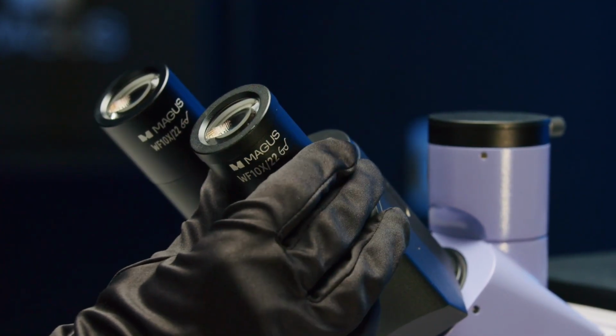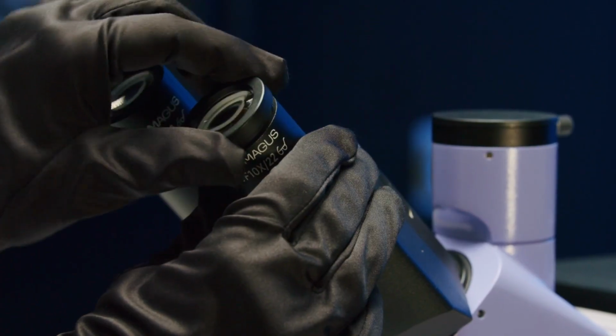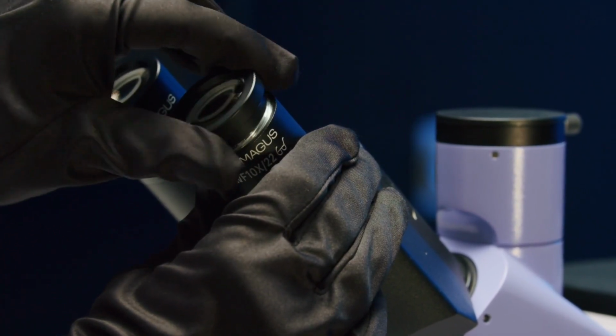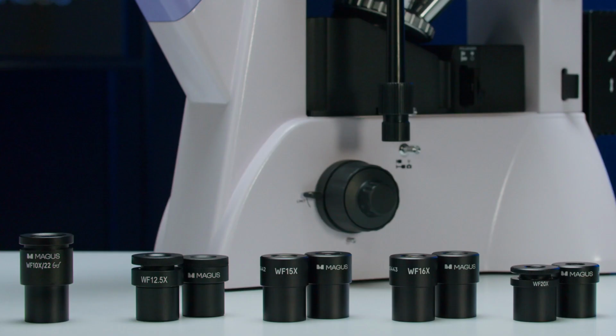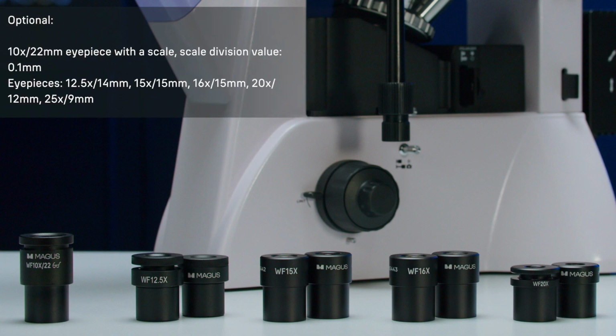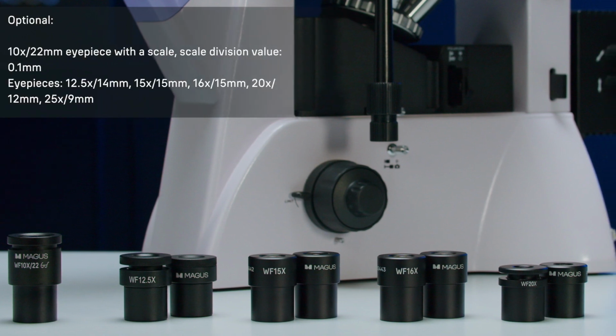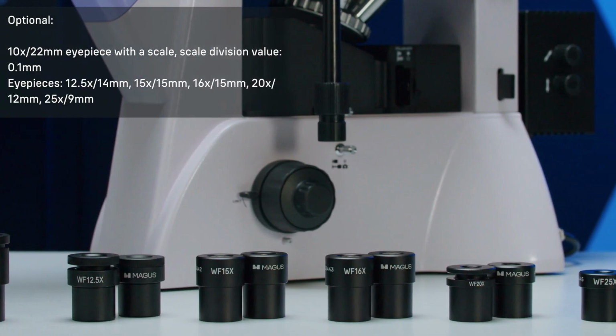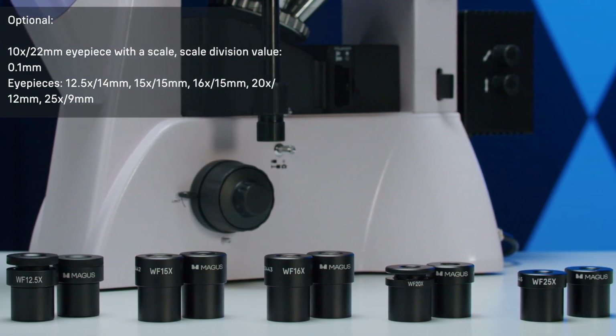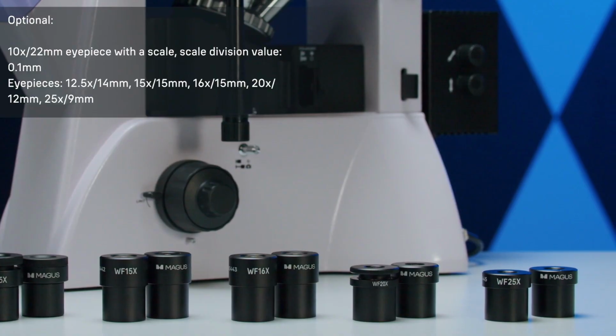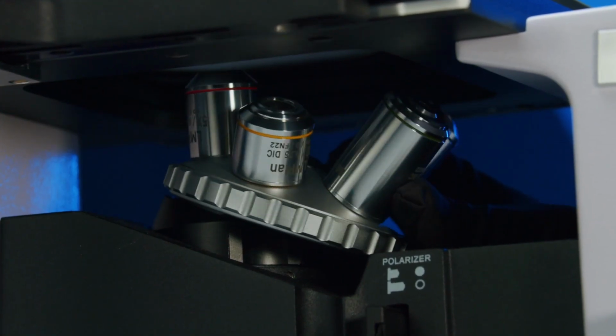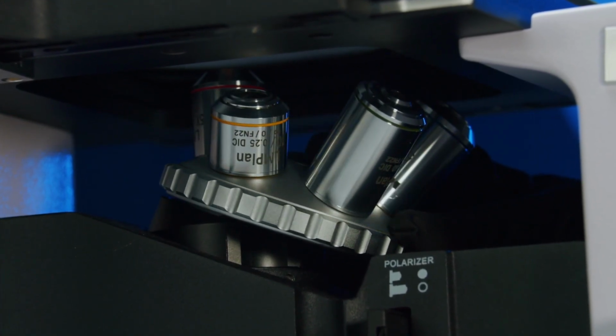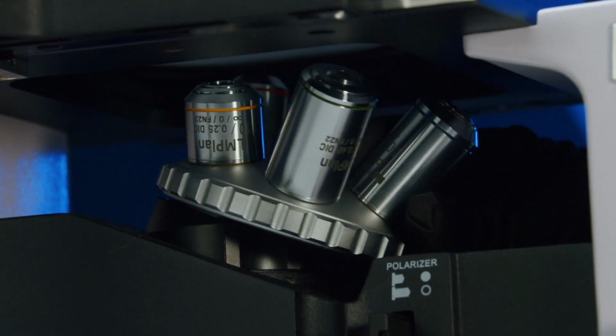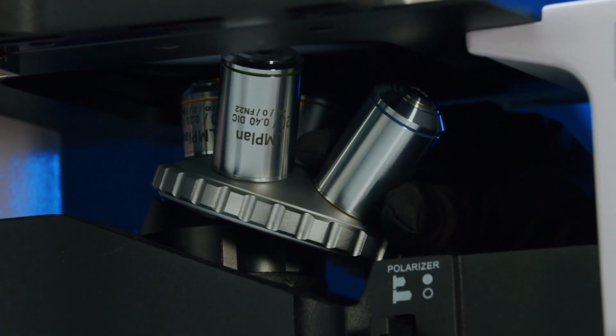The visual adapter tubes do not have a diopter adjustment mechanism. Diopter adjustment is provided on one of the eyepieces. A 10 times eyepiece with a scale is included. 12.5 times, 15 times, 16 times, 20 times, and 25 times eyepieces are available separately. The revolving nosepiece is designed for 5 objectives. The parfocal height of the objectives is 45 millimeters, and the linear field of view is 22 millimeters.